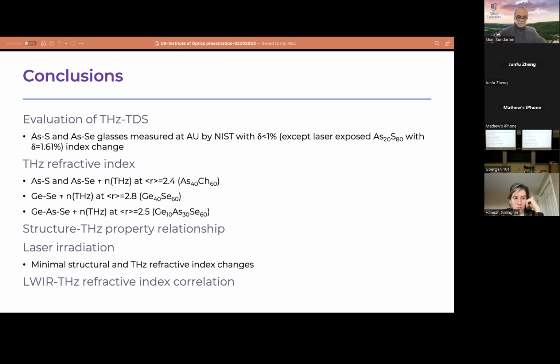So, coming to a quick conclusion, you can see we have evaluated our spectral data, and we have confirmed with the NIST data; we have got a pretty reproducible data set for these glasses. And we could see you have fantastic correlation between the average coordination number of structural units we are seeing in these various glasses and terahertz refractive index as well as long wave IR refractive index. We did a lot of laser radiation studies. We are still analyzing some of the results, but at least for the chalcogenide family, we saw minimal structural changes, and also we saw minimal refractive index changes when we laser irradiated these glasses. And it's a very complicated reason behind why we are seeing minimal changes.